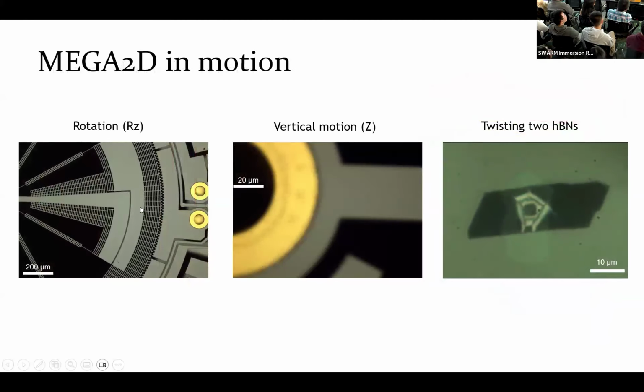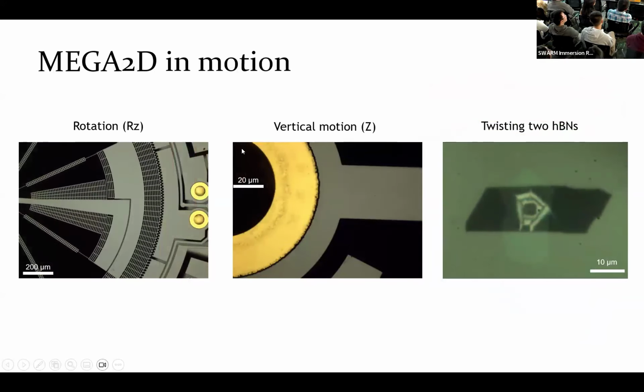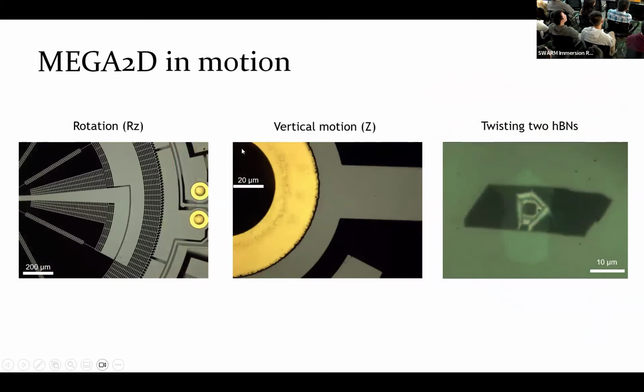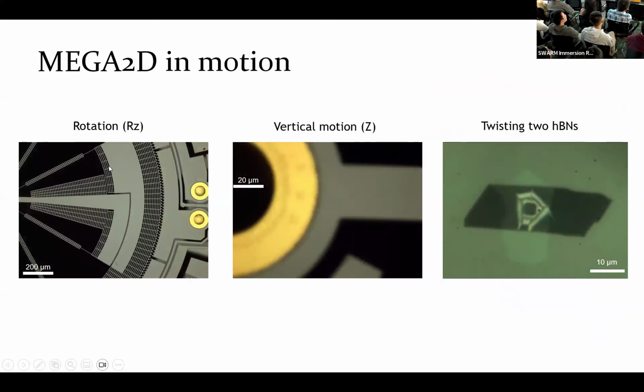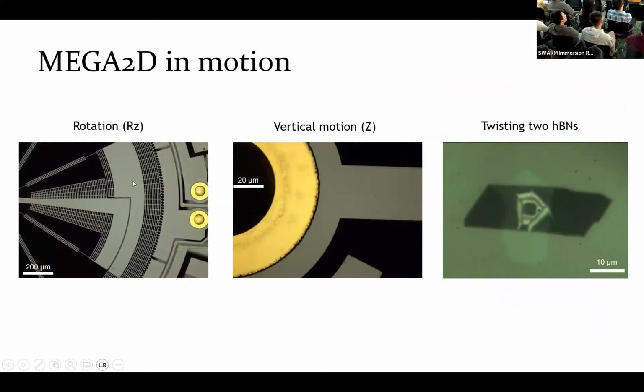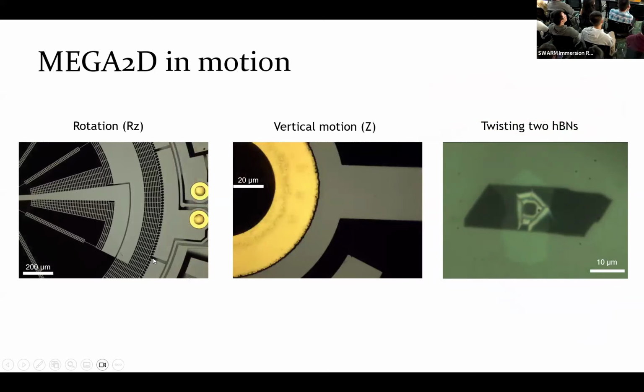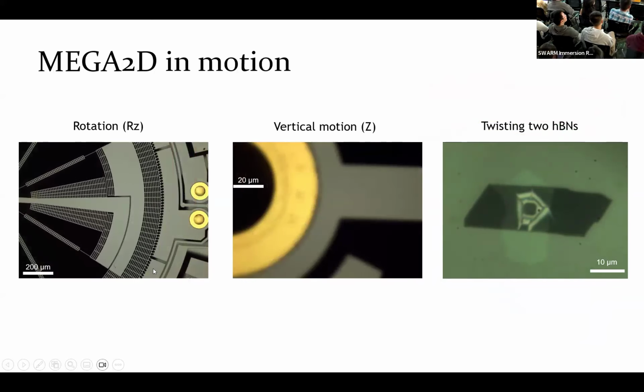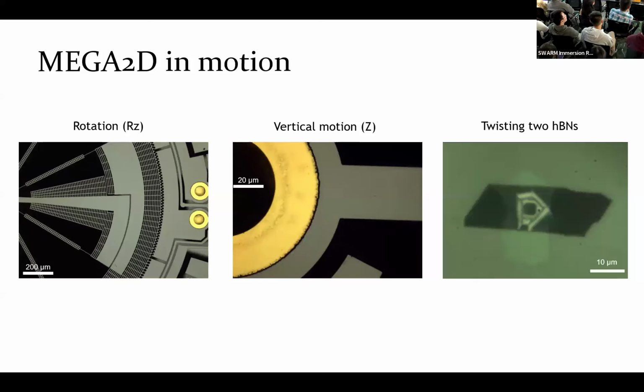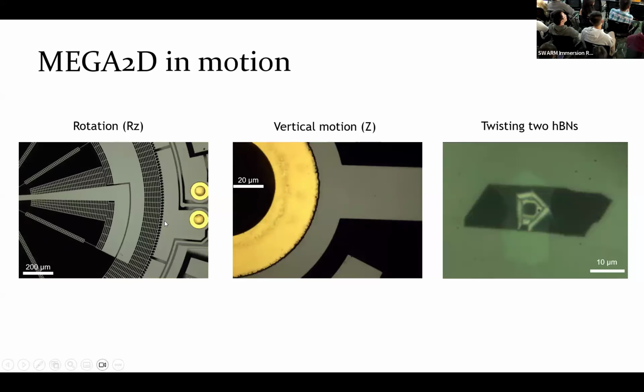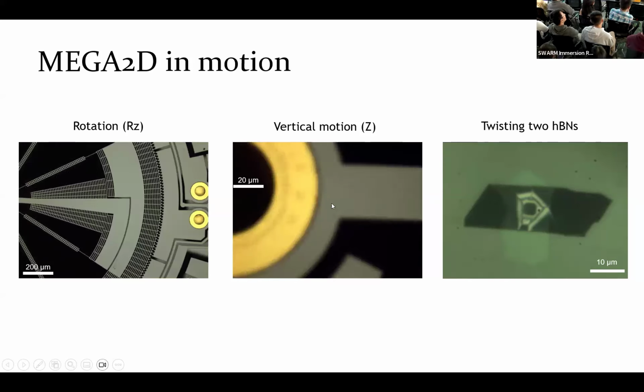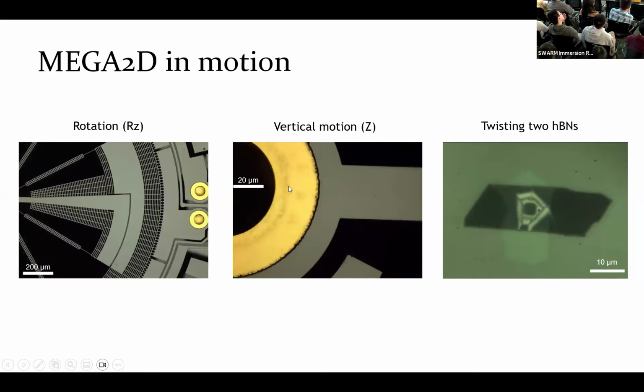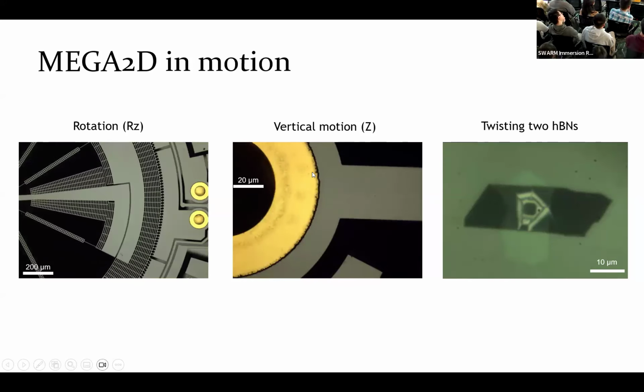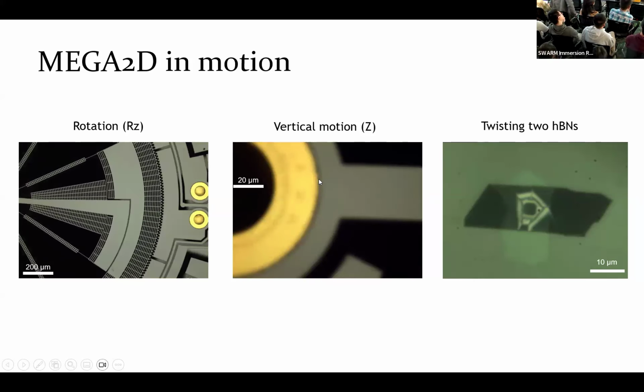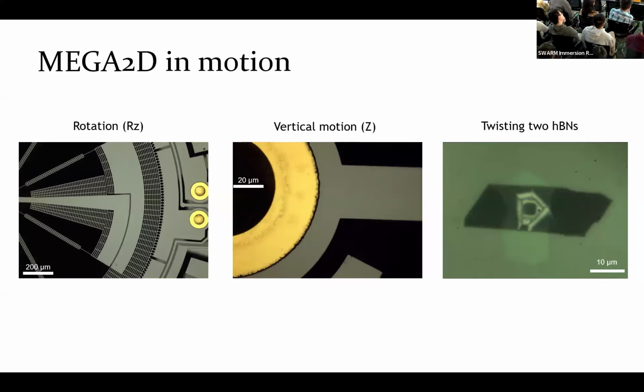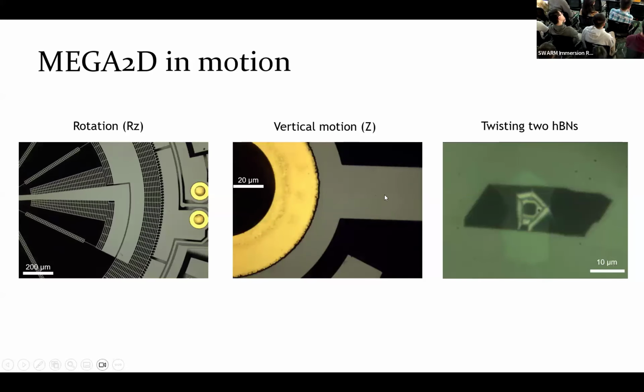And these are some videos of these devices operating in real time. First you're seeing the rotation, which is driven by 3-phase electrostatic actuators, just A, B, C, in order. There are 3 sets of electrodes here, and they achieve the rotation. The vertical motion is another electrostatic actuator, and you can see it moving out of plane. That's why you're seeing it getting in and out of focus in the microscope.